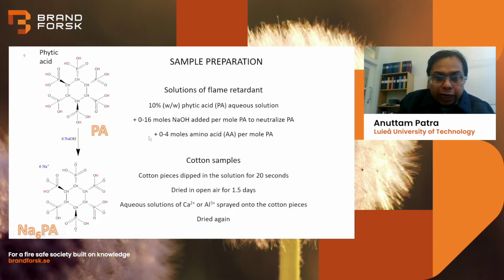In our experiment, we added 0 to 16 moles of sodium hydroxide per mole of phytic acid. And when we also used amino acids, it varied from nothing to 4 moles of amino acid per mole of phytic acid. We used pure cotton samples. We cut them into adequate size and then dipped them in the solution for 20 seconds, then took them out and hung them in air for at least 1.5 days. And when we wanted to make insoluble films, we prepared multivalent cation solutions, and we sprayed that on these samples and again dried them in the air for at least 1.5 days.